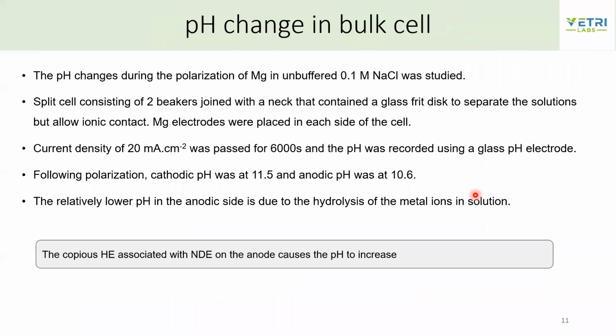In the unbuffered solution, they wanted to see how the pH really changed in an unbuffered condition. For this, they took a split cell and added two beakers with a whole setup. They had magnesium on both sides, and then they tried to study the cathodic pH and the anodic pH and found them to be highly alkaline. What this means is that the relatively lower pH on the anodic side, which is not very high in my view, it's just one point, but they attribute it to the hydrolysis of metal ions in the solution.